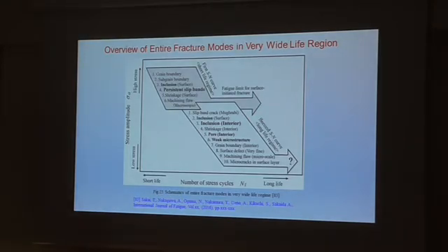Here, let me give an overview of the entire fracture modes in a very wide life region. Very wide life region means including both life regions. You can find very clear duplex S-N curves. Persistent slip bands are the most predominant fracture mode in the first S-N curve.